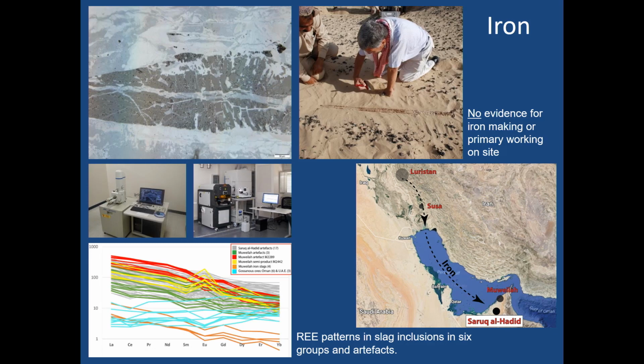And so Ivan's chemical studies of these slag inclusions using ICP-MS and SEM and plotting out the different trace element patterns actually has suggested quite strongly a hypothesis that supports the typological parallels, which is that this material is coming all the way from Iran, probably from Luristan in western Iran, and reaching southeastern Arabia in the early Iron Age as a result of these international trade connections rather than any local development of iron technology.